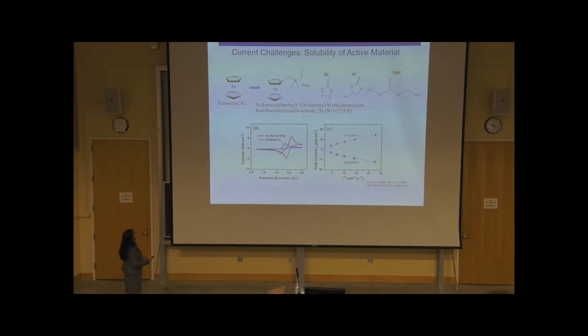So a group at Pacific Northwest National Lab modified this ferrocene molecule by tethering an ionic liquid chain to it, and by using it with TFSI anion, and a solvent mixture of EC-PC-EMC, they were able to enhance the performance, the cell potential, and the energy density of these ferrocene catholytes.